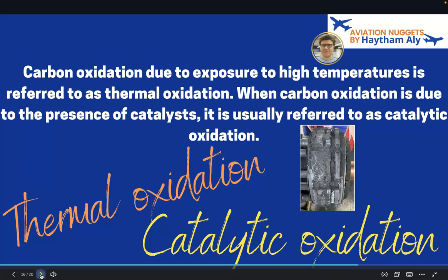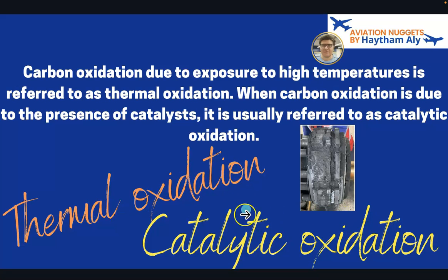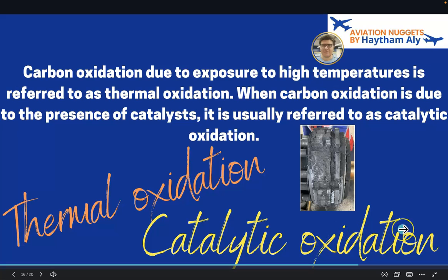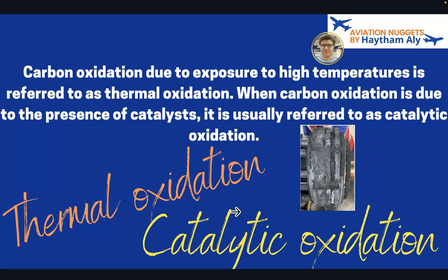Okay, everybody. So these are the two types of oxidation, thermal oxidation and catalytic oxidation. Thermal is due to high temperature, and catalytic oxidation is due to potassium and sodium coming from the cleaning and the de-icing agent. These two types of factor, temperature and the catalyst, increase the oxidation rate so much. So, carbon oxidation due to exposure to high temperature is referred to as thermal oxidation. When carbon oxidation is due to the presence of a catalyst, it is usually referred to as catalytic oxidation.